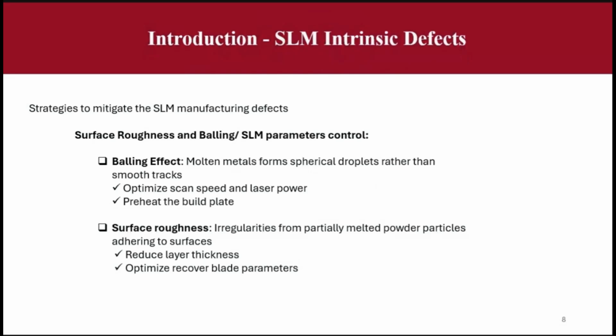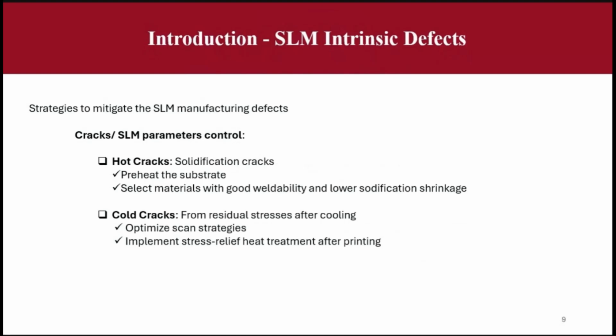The surface roughness and balling. To mitigate this kind of manufacturing defects, for balling effects, we can optimize the scan speed and laser power and preheat the build plate. For the surface roughness, we can reduce the layer thickness and optimize the recoater blade parameters. For the hot cracks, you must preheat the substrate and select materials with good weldability and lower solidification shrinkage. And for the cold cracks, you can optimize the scan strategies and implement stress relief heat treatment after printing.